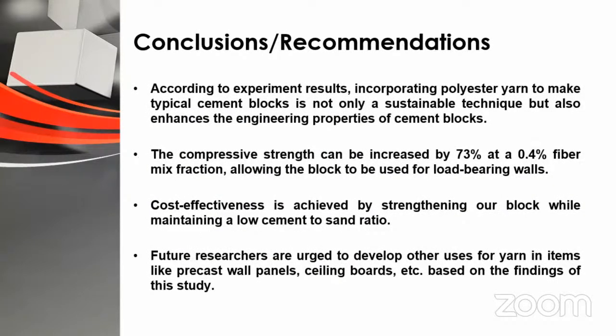Conclusions and recommendations. We have reached several conclusions based on prior findings, which I'd like to highlight. The test findings showed that the characteristics of a typical cement block were not adversely affected by the introduction of polyester yarn. The incorporation of polyester yarn into cement blocks will be able to divert yarn waste to the building sector as a long-term solution to the problem of disposing of polyester yarn waste. The block can be utilized for load-bearing walls and other reinforcing applications since the compressive strength can be enhanced by 73% at a 0.4% fiber mix fraction. Cost effectiveness is achieved by strengthening our block while maintaining a low cement to sand ratio.